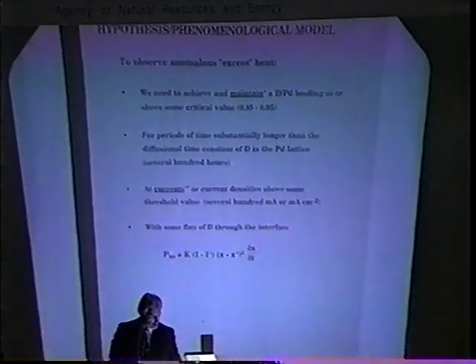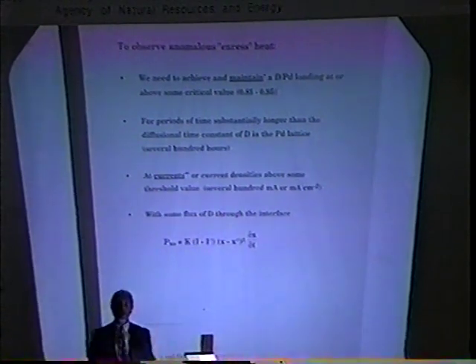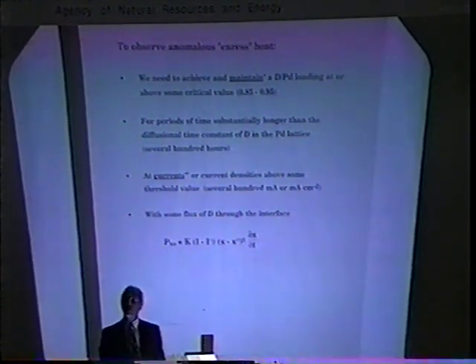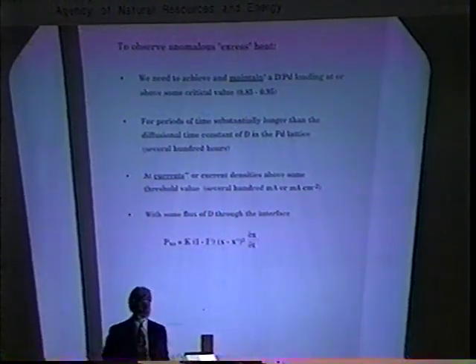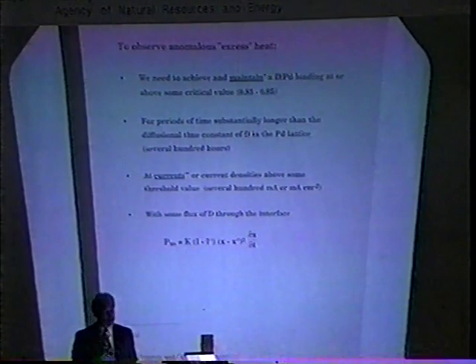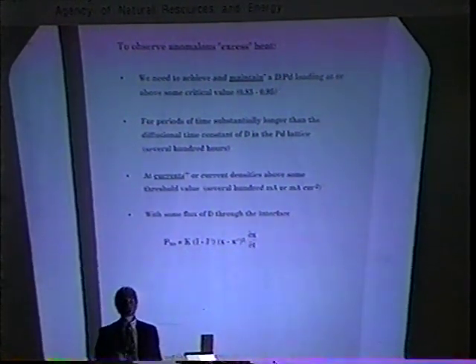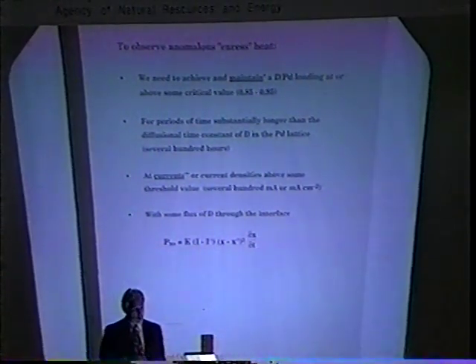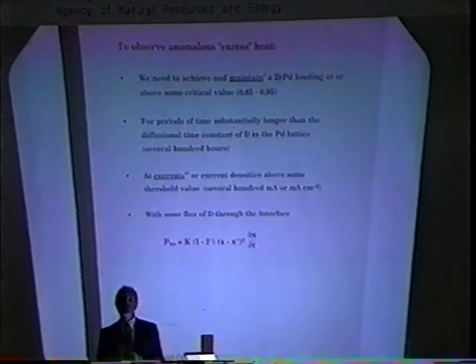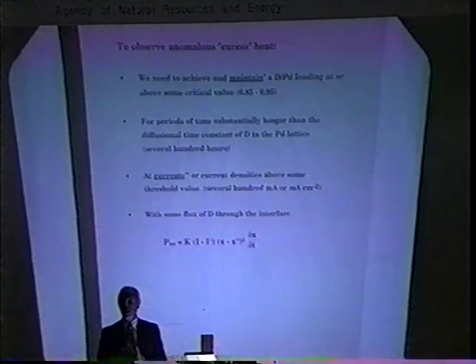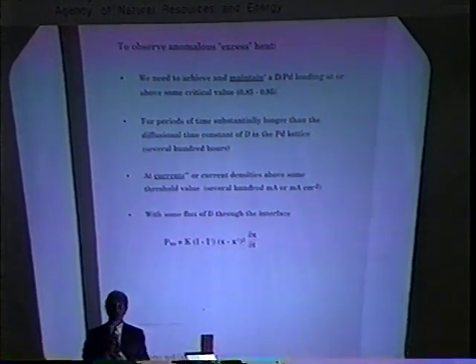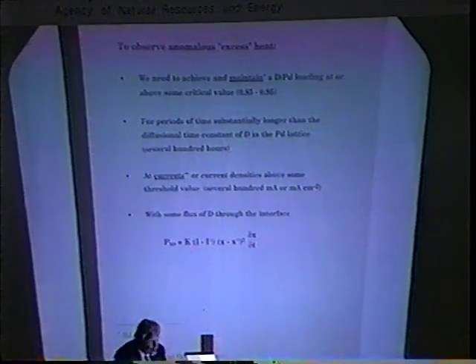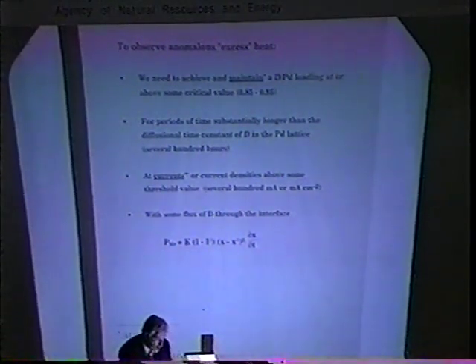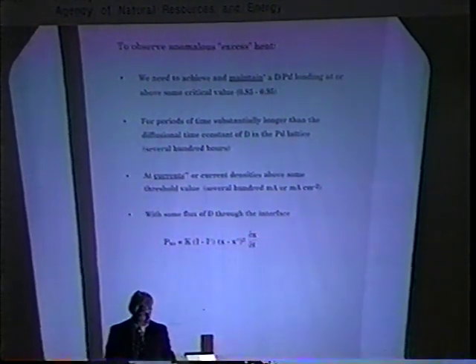I've said this before, I've said it and said it, I'll say it again. Our hypothesis, based upon observation of our own and others' experimental results, a phenomenological model: to observe anomalous, what we call excess heat, you need to achieve and maintain a deuterium to palladium loading at or above some critical value. You need to attain it and maintain it for a considerable period of time, several hundred hours for 3 millimeter palladium cathodes, at currents which are significant, hundreds of milliamps per square centimeter or hundreds of milliamps. We're not quite sure if this is a current or a current density criteria.